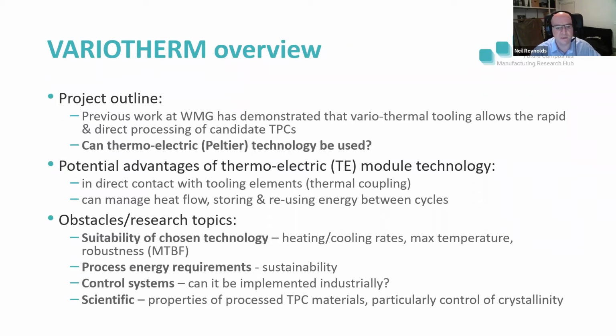The advantage of a thermoelectric module is that the actual heating and cooling element is in direct contact with the tooling elements, that is, the tooling surface. So there's a thermal couple, and we can use the thermoelectric module to manage the heat flow. So we can actually store and reuse heat energy between cycles. There's existing technology that uses fluid coupling for the same thing, so air and liquids to move and heat tooling surfaces. But the idea here is to actually move the heat around in the tooling system.